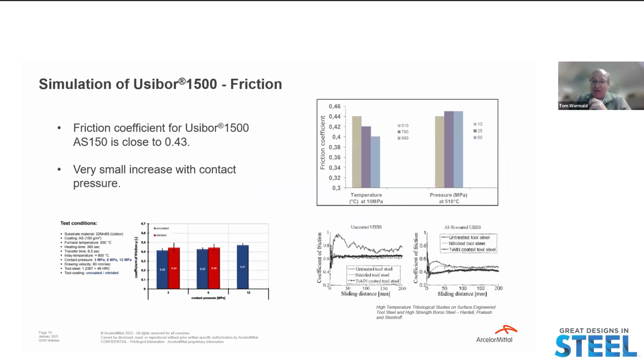Friction values to be used in simulation of the hot stamping process are an area of development and research. Friction values are certainly much higher than the 0.1 to 0.15 values that we're used to for cold stamping. For hot stamping, accepted values tend to range between 0.35 and 0.5.